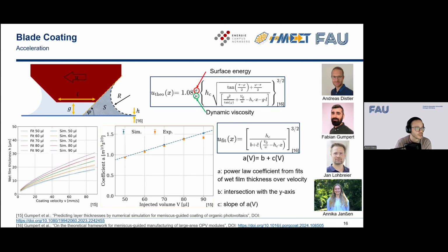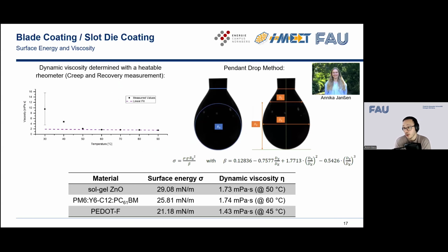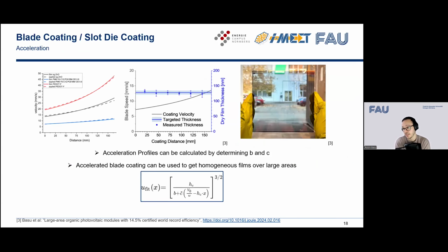Okay, so with the input parameters that we have here, we now needed them for our systems, so for the inks that we use. We did creep and recovery measurements with the rheometer to find out what the dynamic viscosity was. And we used the pendant drop method and the formula that I gave you underneath the droplets to calculate the surface energy. With those input parameters, we were able to use CFD simulations again to get our B and C vectors. And with that, you can see that the applied profiles that we used to get the homogeneous layers fit very well to the simulated ones according to the fit.